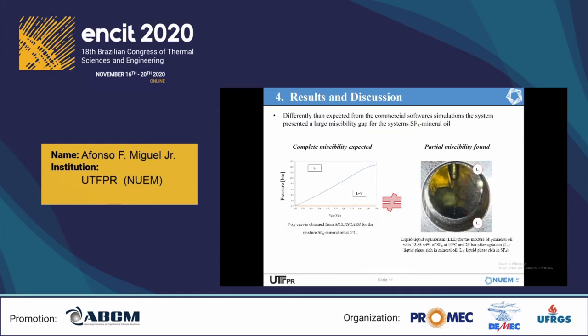Differently than expected from the commercial software simulations, the system showed a large miscibility gap. On the left side of your screen, you can see the PX diagram predicted by the commercial thermodynamic software Multi-Flash, which anticipated a complete miscibility of the mixture. Such behavior was not found in reality, as you can see in the image on the right side of your screen, where you can identify two liquid phases — one rich in mineral oil, the upper phase, and the other rich in liquid SF6, the lower phase.